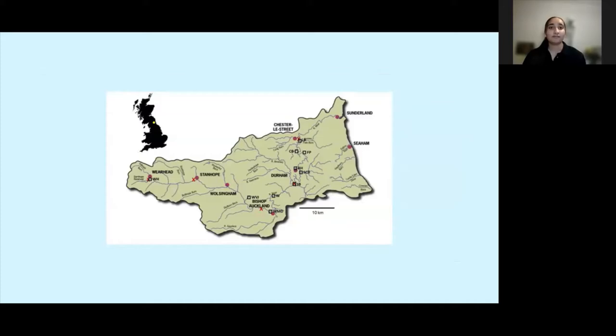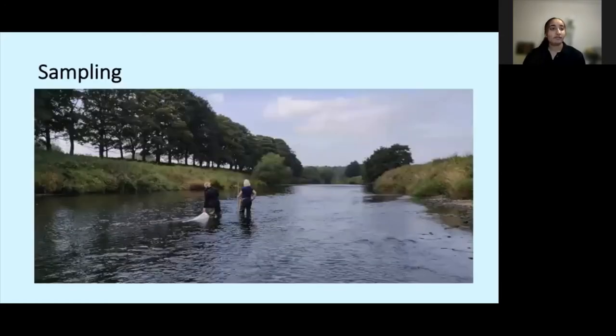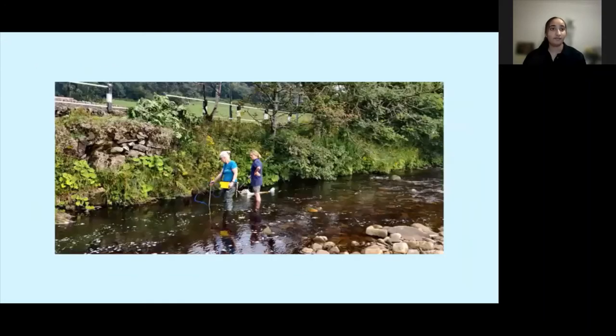After the correct time passed we made our way to the river bank and then we used filtered water to spray the contents of the net into the cod-end jar to ensure any microplastics were not left behind in the net. We repeated this for the rest of the samples and time periods and determined 20 minutes would be most appropriate for sampling.